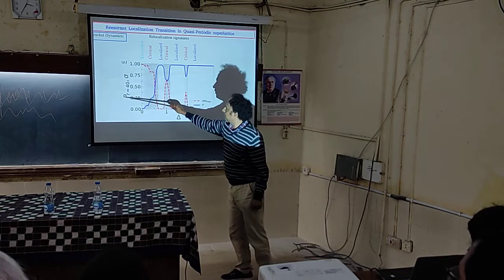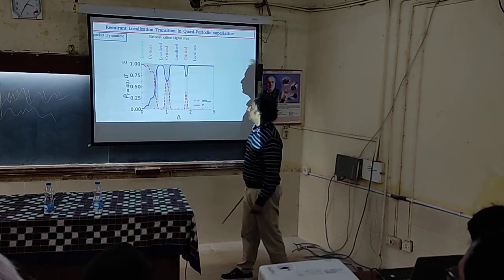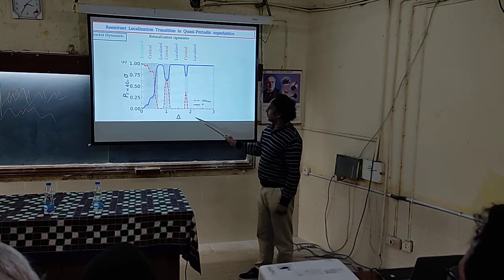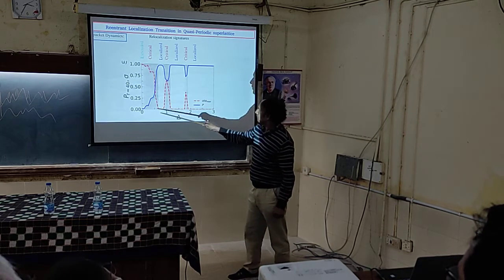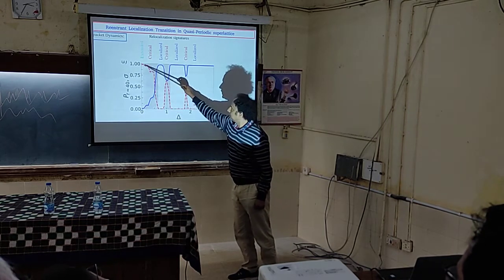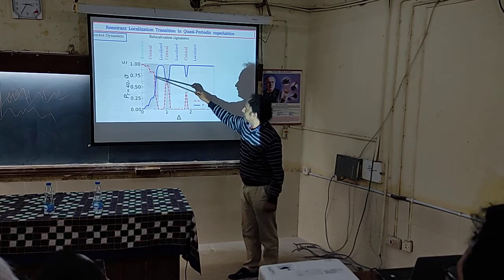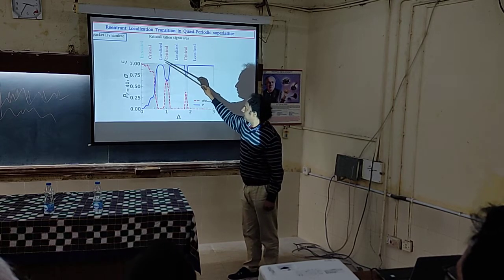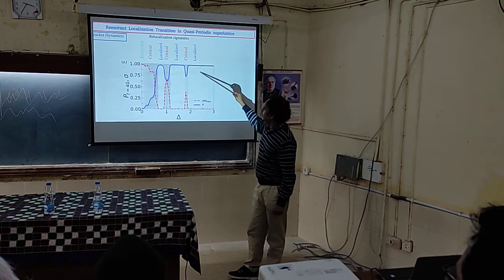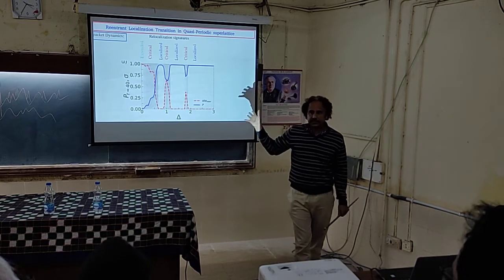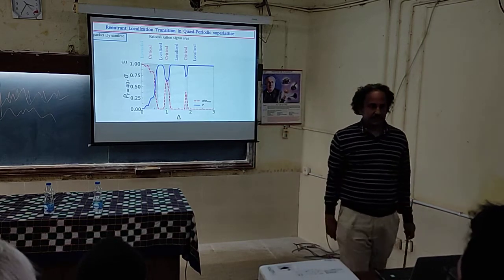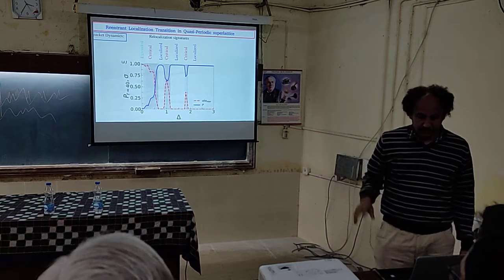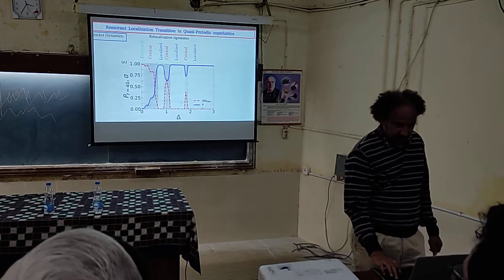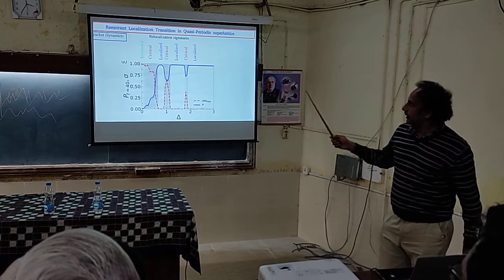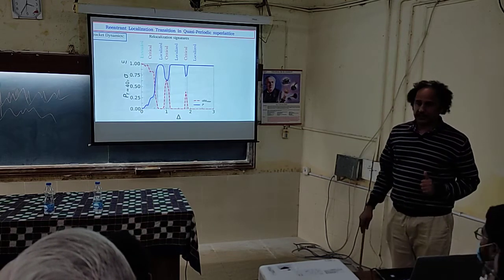If you plot the survival probability and the root mean square displacement with respect to this delta for a fixed disorder strength, you can see that this is 0, this is finite. So this path is extended, this is critical, this is localized, critical, localized, critical. These are the signatures which can be readily seen in cold atom experiments, even in superconducting circuits.